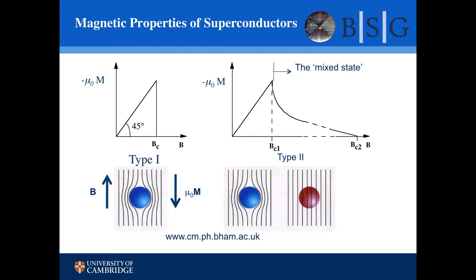And if there are no demag effects, then this angle's 45 degrees. So if we apply half a Tesla, our superconductor generates minus half a Tesla. So that means since flux has a beginning and an end, our external field's in this direction, our internal field is equal and opposite to our external field, which means the field in the superconductor is zero. So one peculiar property of a superconductor is that it will expel magnetic flux from its interior. It's called the Meissner effect.